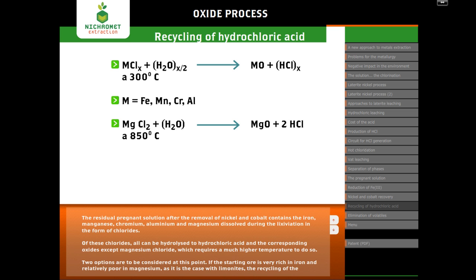If, on the other hand, the starting ore is rather rich in magnesium and low in iron, then the solution can be freed of iron by pH adjustment and concentrated to obtain the purified magnesium chloride. This magnesium chloride can either be recycled to the production of hydrochloric acid, as indicated before, or used as a source of magnesium derivatives, such as magnesium oxide.